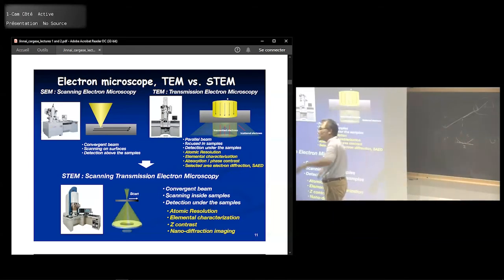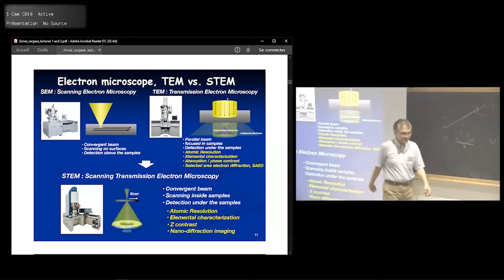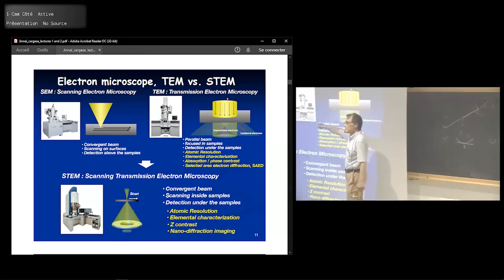About the sample preparation, because for TEM and SEM they'd be very different. And what about STEM? It's the same thing. For the TEM, as you know, we typically normally use cryo microtome. It's like a cutter, the knife cutting the cheese. Okay, the thickness of the sample will be like 100 nanometer, 150 nanometer. So it's very thin sample, and the same sample can be used for the STEM too. And for the SEM, you don't have to use the microtome, right? You can just make the surface. That's all.